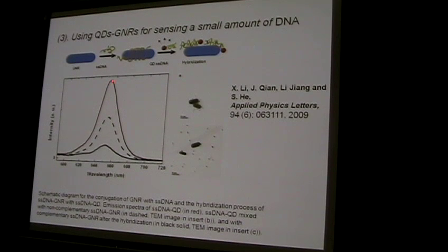And this is the original quantum dot fluorescence, and this is the maximum quenching when we have the maximum overlap of the absorption spectrum with the quantum dot spectrum. And in the middle case, the dashed case is when these DNA are not complementary to each other, and then these quantum dots are just swimming around rather than attached to the surface, because there's no hybridization. And then the quenching effect will not be so significant. You see it in the middle region.